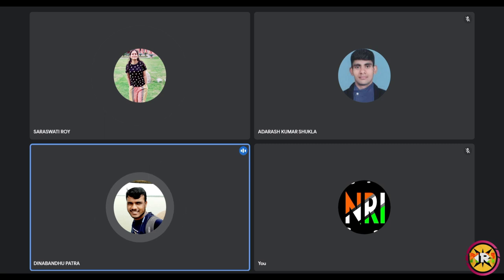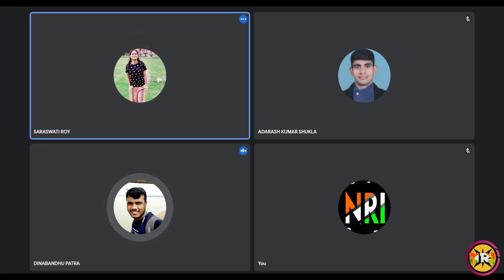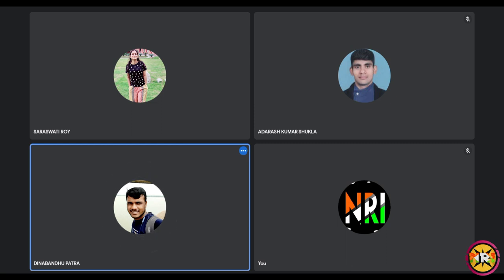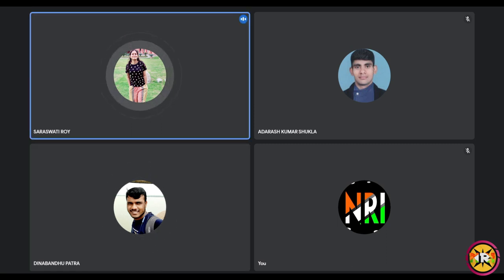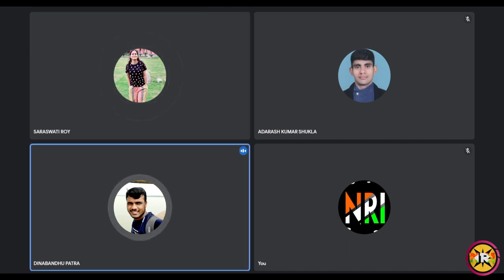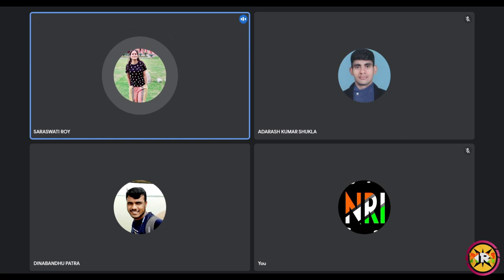Okay, and in TEM images, you got a very small size of the Co3O4 for the SCS sample, like 2 to 3 nanometers, I think. Yes. But when we saw in the same images, it looks like a chunk kind of thing, right? Yes, due to the calcination issues. So why in TEM images are we not seeing those kinds of things? Actually, I have not done it in 200 kV. It was a 120 kV instrument, so the clear image and all. When you were asking why this chunk kind of picture is not clear in TEM, actually it was a biomolecule TEM, so I did not get such a good structure.